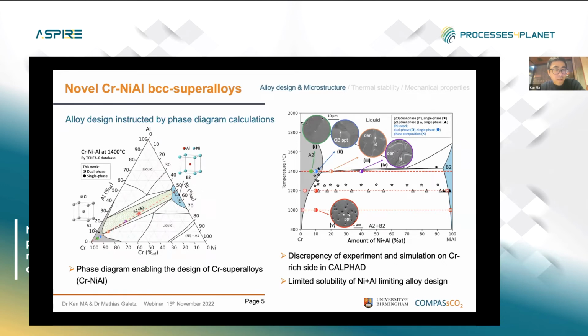So if we draw the vertical section of this line, we can obtain this pseudo binary phase diagram of chromium and nickel aluminide, and the form of this phase diagram enables a quite classic superalloy design, which means we can heat treat the sample at high temperature to achieve a single phase area, then to another lower temperature heat treatment to precipitate out all the precipitate which strengthen the material.